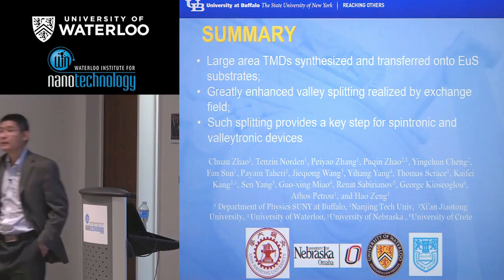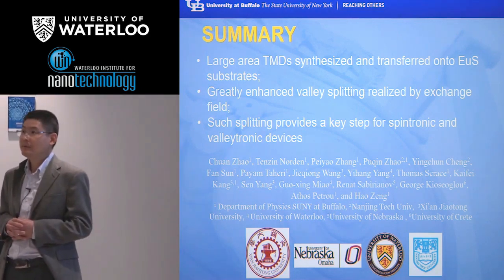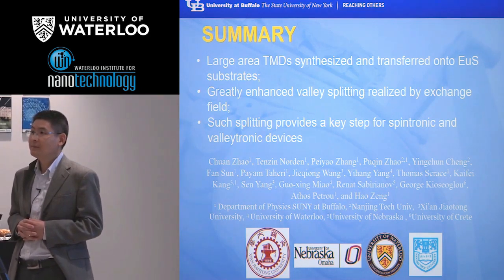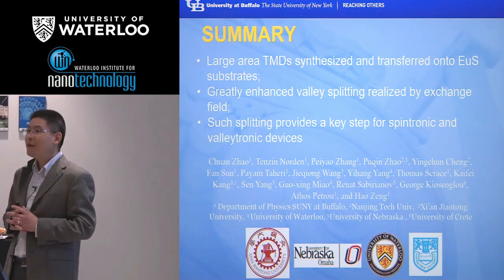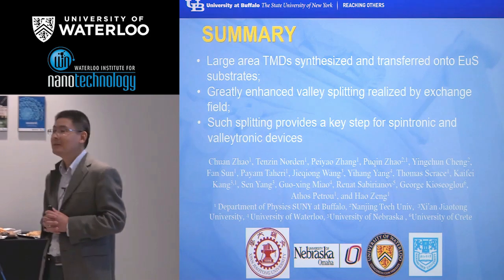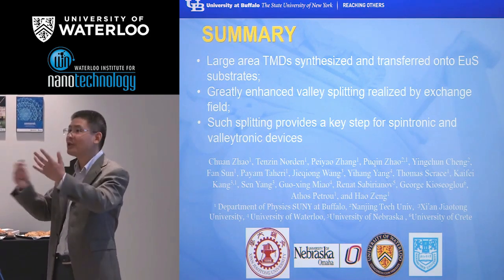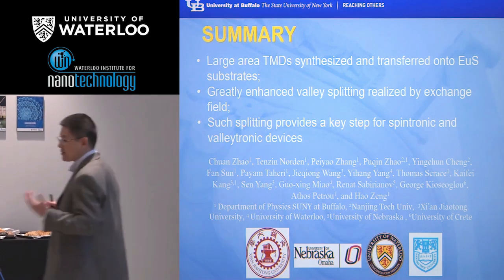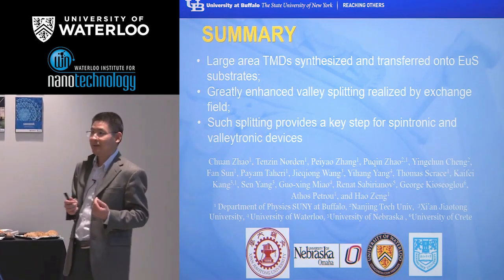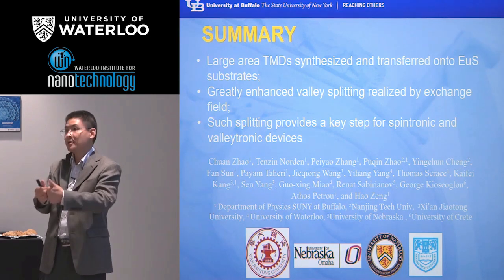So maybe along those lines, a couple of questions. So even if you do have a magnetic doping, you would still have to rely on some form of long-range interactions. Very good, yes, right? Otherwise, you end up with paramagnetic centers, which could actually decay very quickly. That's right. So I don't know if that would help you actually with this. That's why it's so challenging to do magnetic doping, right? Because you have to have high enough concentration to induce this long-range coupling.